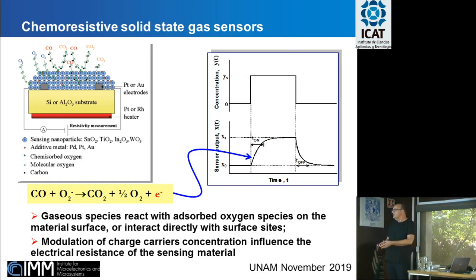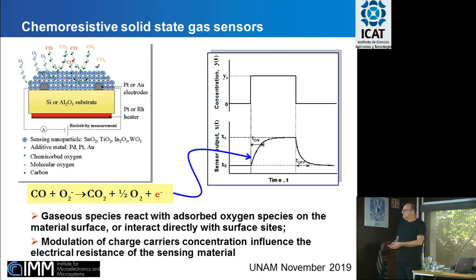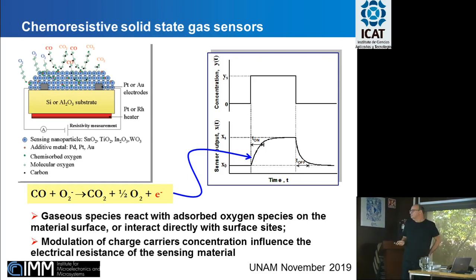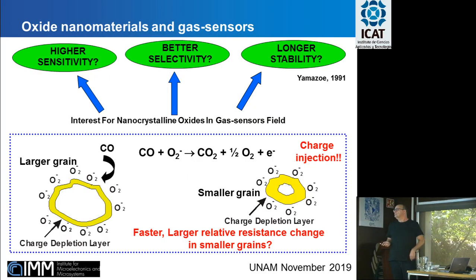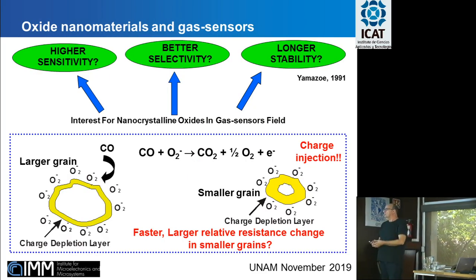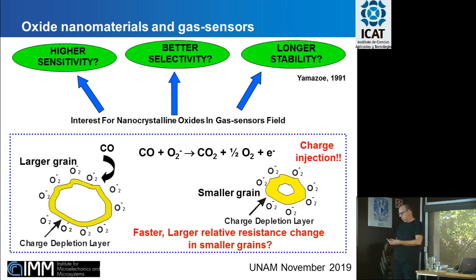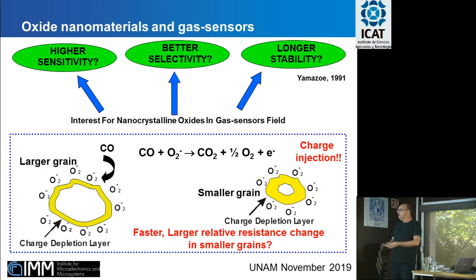Or, shortly, we have a change of the current or of the resistance of the sensor when it is exposed to a given gas. Which means that, in principle, we can detect the presence of a given gas by simply following the change of the electrical current crossing the device when it is exposed to the gaseous analyte. More or less 30 years ago, there was an interesting work by Yamazoe in Japan which suggested that nanocrystalline materials could give rise to improved performances in gas sensors in terms of higher sensitivity, better selectivity, and longer stability.